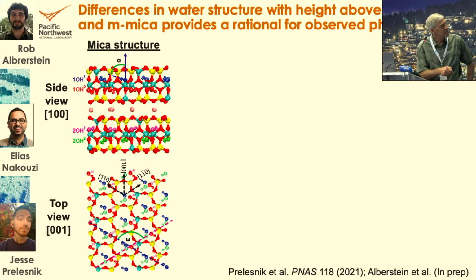So there's the mica structure. It's a layered compound. Here's the layer that we're interacting with. But below that layer are these OH groups. And you see they point in a certain direction. And if I look down on the surface, you see the blue, the green, the red, and the pink. Those are OH groups in 4 successive layers. Now, they only point in one of 2 directions. This direction or that direction.